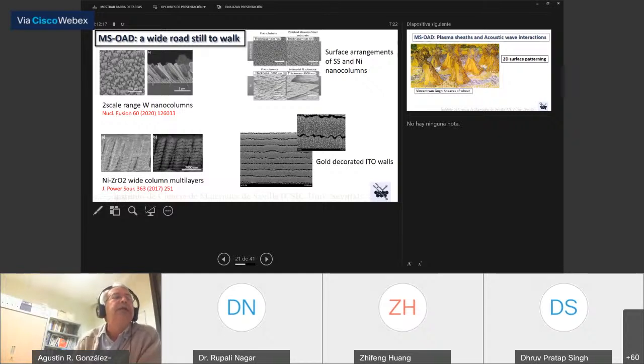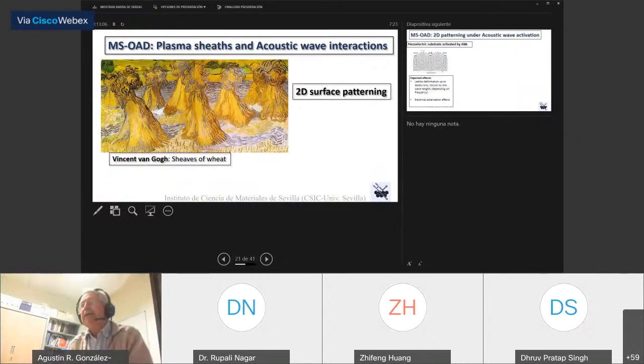Just as an example, I cannot go into detail, but for example, these are a two-scale range of tungsten nanocolumns. Look here that the separation between these nanocolumns is 1.5 microns. And this is possible because we have a very strict control of the position of this nanostructure formed by very wide nanocolumnar structure made of nickel zirconia structure. Of this, what we call ITO walls, decorated with gold nanoparticles, where the distance between these walls here is some 100 nanometers, and the size of the walls is some microns. As I said, I cannot go into details because I would like to concentrate in the last part of my talk, which is directed to the possibility to produce some 2D surface patterning using magnetron sputtering deposition.